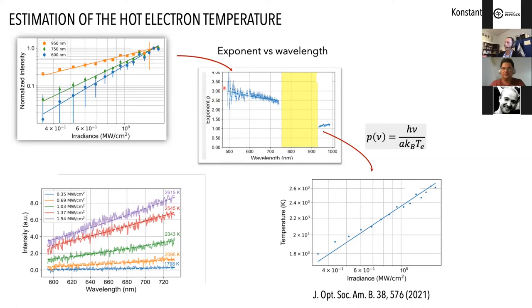And you see that we recall what we've seen in Lupton's paper that I was mentioning before. We have a linear dependence with wavelength for the anti-Stokes part of the spectrum, and this is sort of linear with wavelength for the regular photoluminescence on the Stokes side. So once we get this exponent, it is expected to follow that relationship. We fit the slope here, and fitting the slope, we can extract the electronic temperature as a function of irradiance. And what you see here is basically this dotted line.